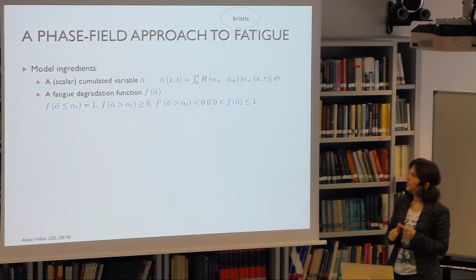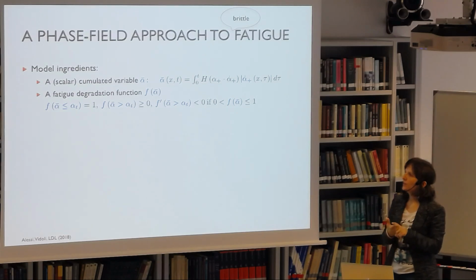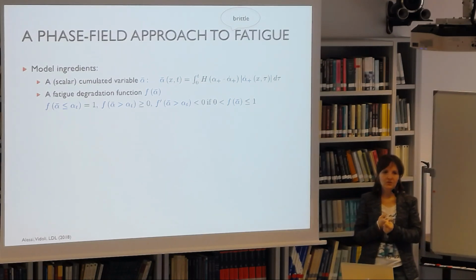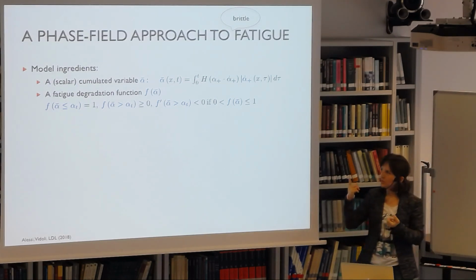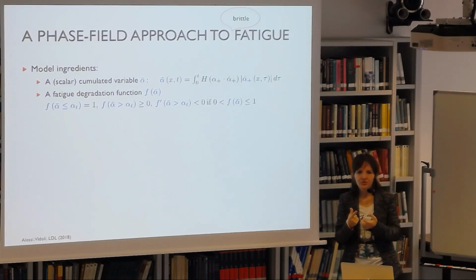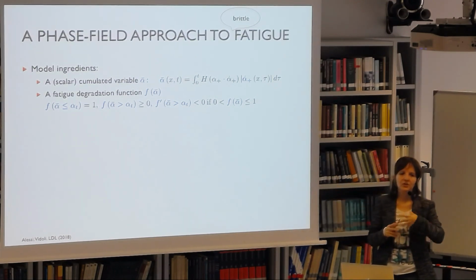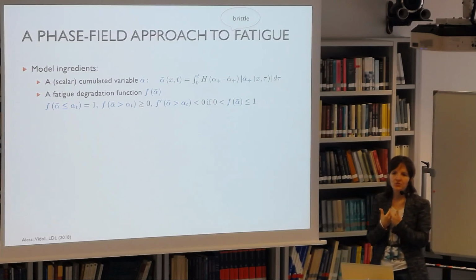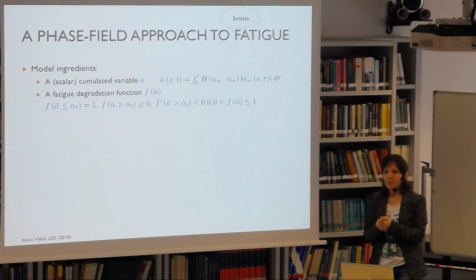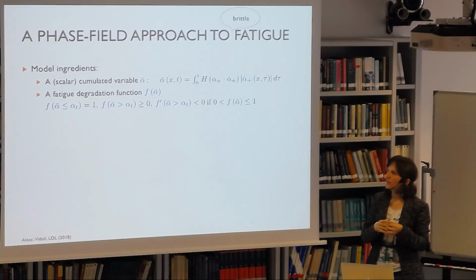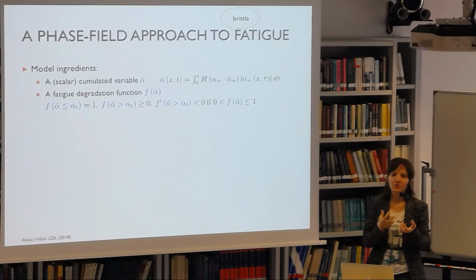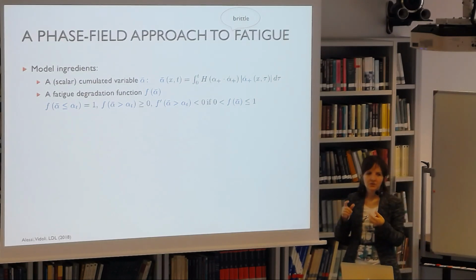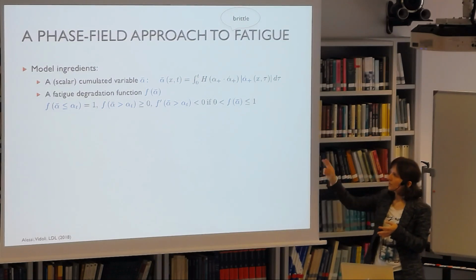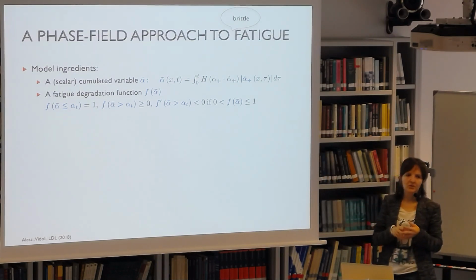So this was the first ingredient, the accumulated variable. Then you need a fatigue degradation function that is responsible for reducing, as I'll show you in a second, the fracture toughness of the material. This is the approach that we are following. We consider fatigue effectively as a degradation of the fracture toughness, and the degradation of the fracture toughness is performed through this fatigue degradation function.